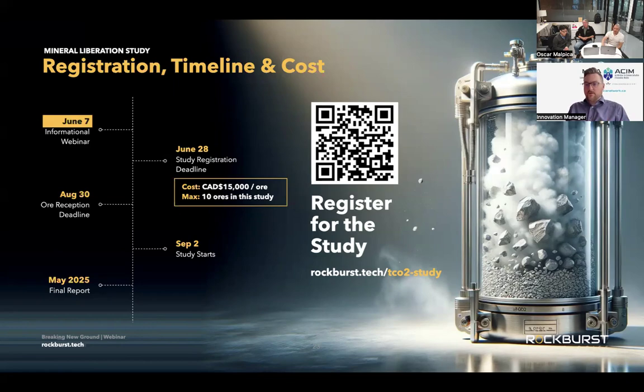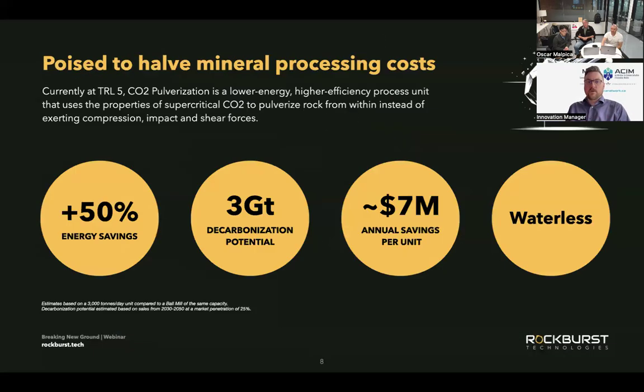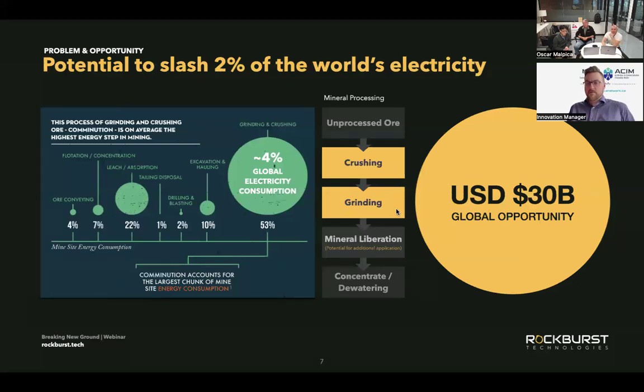Where does this fit into the flow sheet, and what equipment do you think it could potentially replace? And then what throughput do you envision this technology could be capable of? Right. On the flow sheet, it would potentially replace SAG mills and ball mills as a combined unit. Potentially, it could be just a ball mill if you want to use the prior stages. Say you have an HPGR and ball mill flow sheet, we could be looking at replacing the ball mill. So it could be a combination of say 150 to 100 millimeter size feed, all the way down to final product. Or our earlier estimations are, let's go for the finer grinding where the energy is the most intensive, so sort of 25 to 20 millimeter or smaller, maybe even 10 millimeter feed.